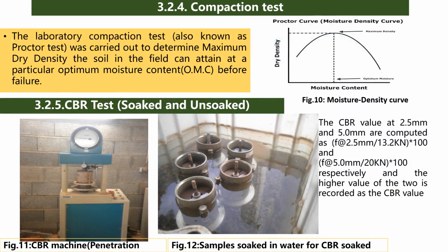California bearing ratio tests are of two stages, the unsoaked and the soaked. The difference is that the soaked tests were carried out after being immersed in water for about 48 hours, and the essence of this is to know the effect of water on the strength of the subgrade soil.